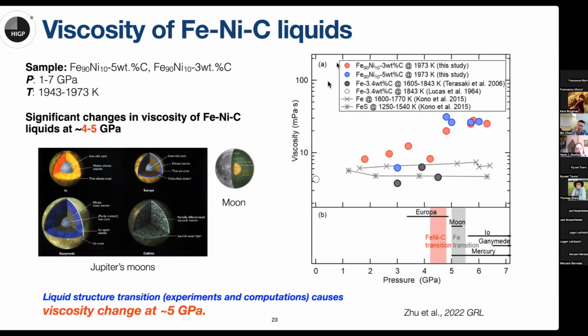So this is our experimental result. We measured the viscosity of iron nickel carbon with 3% carbon and iron nickel with 5% carbon at around 2000 Kelvin. We find a substantial factor of 2 to 3 increase of viscosity across this 4 to 5 GPa. In previous work, we found that there is a structure transition in the liquid. And this jump in the viscosity would have some implications about the dynamics of the planetary cores.